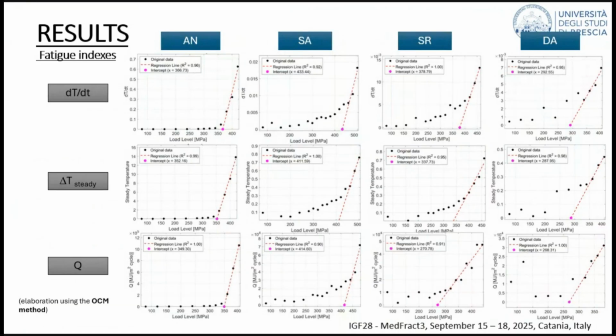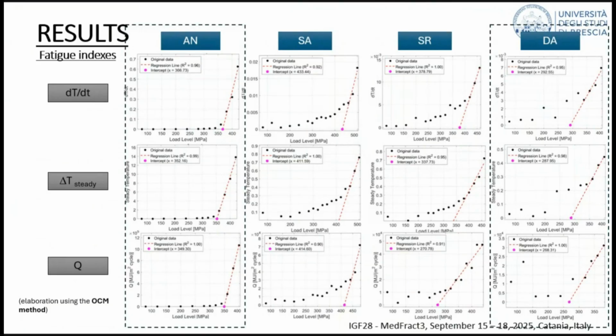So in this slide, you can see, let's say, a general summary of the results. The point of this slide is just to show one result which was not obvious at the beginning, at least for us, and it's that the type of diagram that you get is actually comparable qualitatively with what you get for conventional metals. And that is important because it's possibly an indication that the method can work for additive manufacturing also. The second observation, you can see that the curve changes depending on the material condition. For example, for the annealing condition, which is the first one, you have a different type of response in comparison with the last one, which is direct aging, which is a very different heat treatment. So the second indication is that the method is actually sensitive to the material condition.